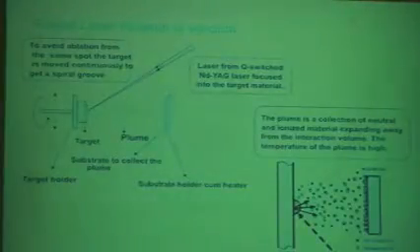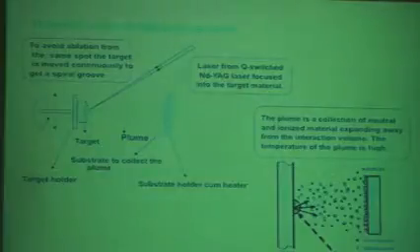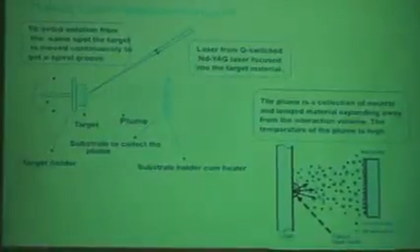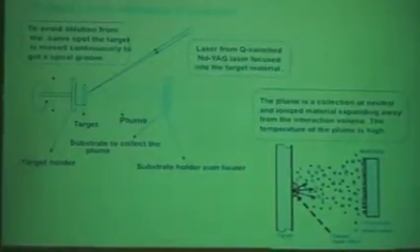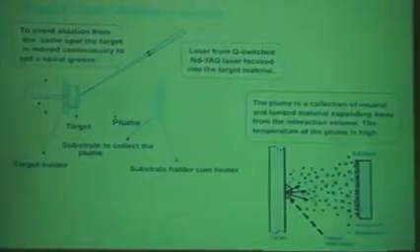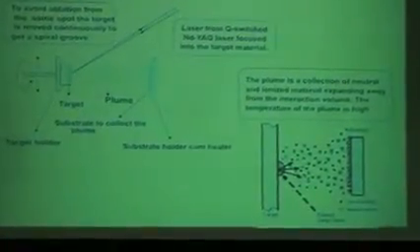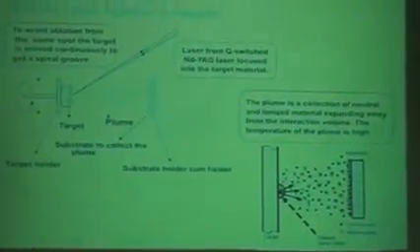Let's leave the arc discharge there and move on to laser ablation, which is even more interesting. Of course, the instrumentation required here is quite expensive. You need a laser which can shoot out pulses, photon flux, very high energy density. Typically one uses Nd:YAG, for example, or excimer laser. With Nd:YAG you are relying on the 1064 IR photons or the frequency doubled 532.